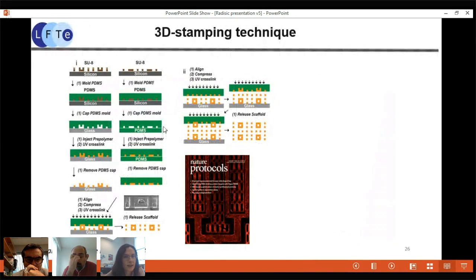And what you can see here is that he starts with standard SU8 molds, and then he creates layers of angiochip scaffold through capping the PDMS mold on the glass. And then he perfuses the POMAC polymer. He cross-links the polymer with UV illumination, and then he removes the mold. And upon cross-linking, the polymer will remain bound to the glass. And then he can build that up in the Z direction using the next layer.